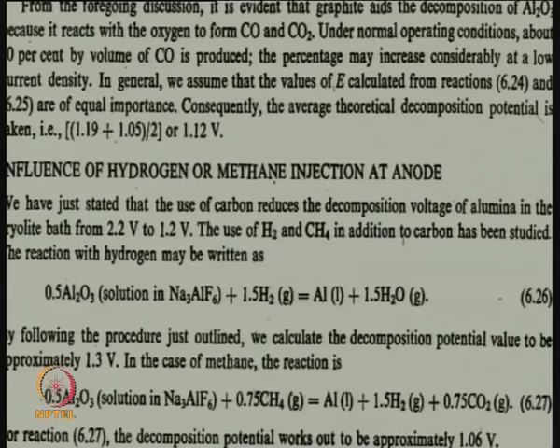So, we can calculate: we have one reaction, and to that we combine what happens if you bring in hydrogen. So, this will react with hydrogen producing aluminum. We can calculate its voltage will come to about 1.3 volts, which means it is not very much better than what we had for graphite. Its only advantage would surely be that it will lower the consumption of graphite, but it will not bring down the voltage.